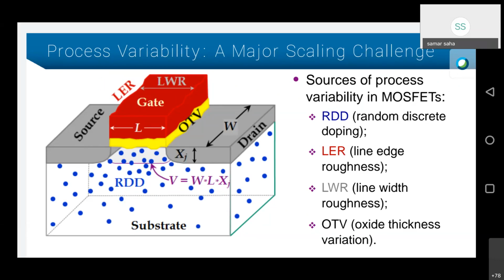So as a result, it causes random dopant fluctuations, or RDF, or RDD. RDD is random discrete dopants. So these are discrete dopants, and that causes threshold voltage variation. In addition to that, because of the lithographic process, we have oxide thickness variation, which is OTV. And then, also with the lithographic process, we have this rugged or rough edge. So that gives you line edge roughness, and also line width roughness. So all these things come into play, which contributes to the variation of device performance.